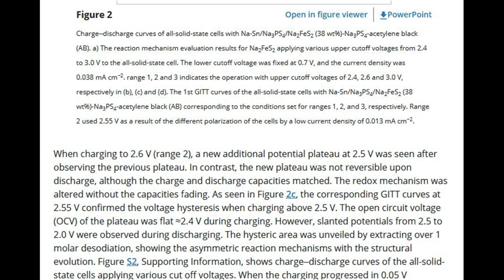Range 2 used 2.55 V as a result of the different polarization of the cells by a low current density of 0.013 mA cm-2. When charging to 2.6 V, range 2, a new additional potential plateau at 2.5 V was seen after observing the previous plateau. In contrast, the new plateau was not reversible upon discharge, although the charge and discharge capacities matched. The redox mechanism was altered without the capacities fading.